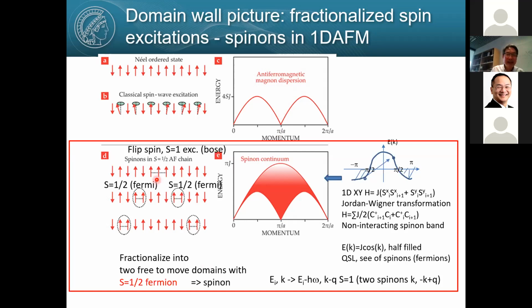This spin used to be down, and you just flip it. So the spin changes from -1/2 to +1/2. There is a spin change of S equals 1. So this is an S equals 1 bosonic excitation. By flipping this, you have two domain boundaries with two neighboring spins. But this is a specialty of 1D: those two domain boundaries can move in opposite directions without costing any energy. So the domain boundaries can move around freely.